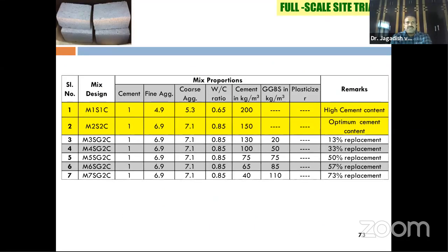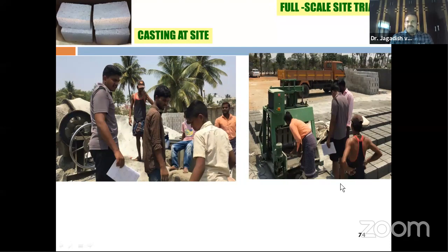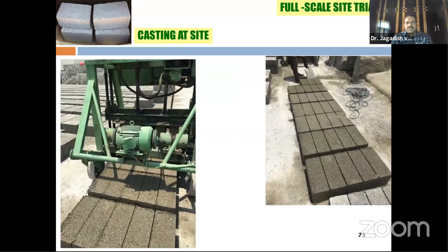These are the full-scale trials we have conducted by taking the optimum mixes from the laboratory trials, wherein we have considered 13, 33, 50, 57, and 73 percentages. This is a casting done at one of the solid block manufacturing plants. This is an egg laying machine wherein you continuously make the blocks. Using all these mixes, they made more than 300 blocks at the site. So this is how the casting at site is happening. These people went on Saturdays and Sundays and did it. To tell you, it's a beta project, by the way.